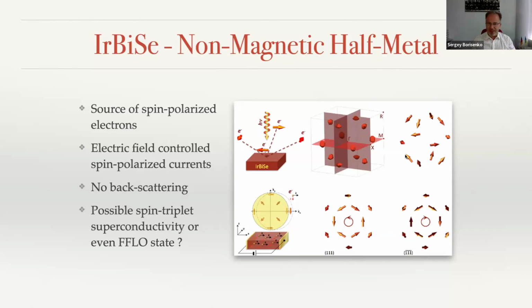There is no net magnetization, but I thought it is in the spirit of altermagnetism, where you have spin splitting in the reciprocal space but no net magnetization, and the material remains non-magnetic. We also noticed that this could be a nice material with absence of backscattering, because there is hardly any mechanism for it, and possibly there could be electric field controlled spin polarized current, because if we apply an electric field, one would see that the rest would be compensated, and these two components would give us the spin polarized current.